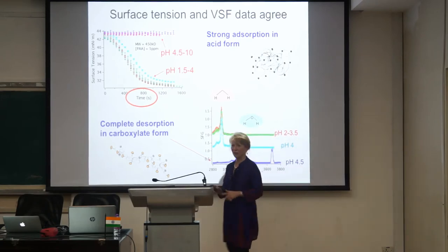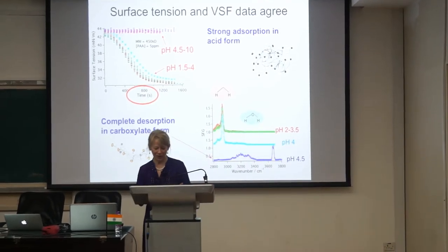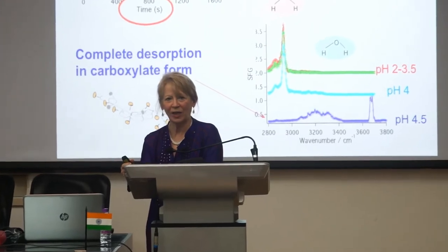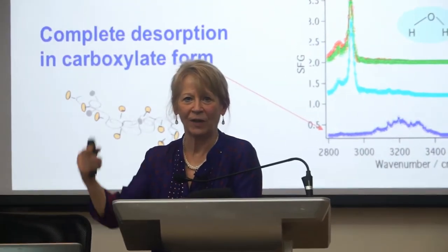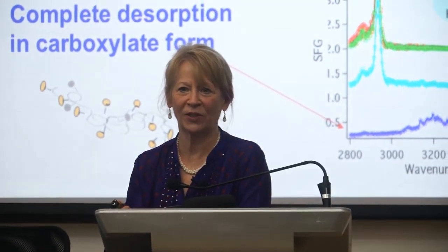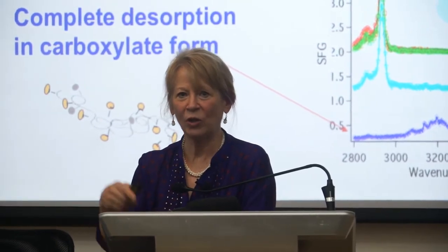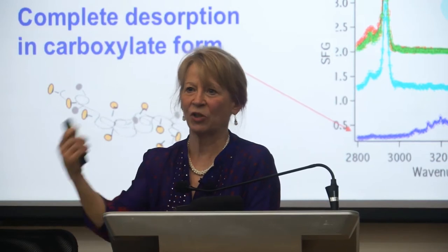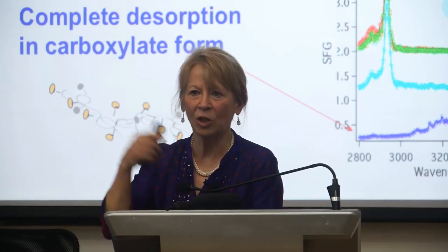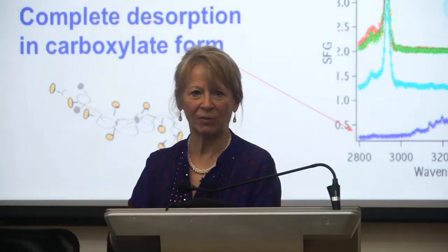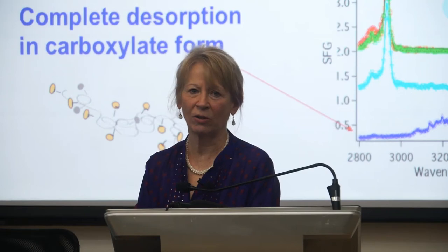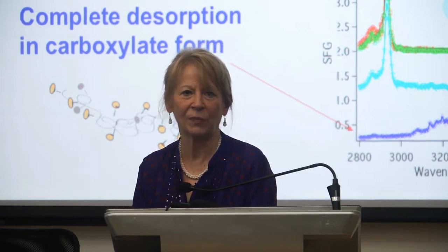So here's the deal. Normally when you think you're going to measure something, you're going to get a signal every time something goes there. Normally you think as more and more stuff goes down that your signal gets stronger. So if I'm measuring how much stuff is there and my stuff is related to my signal, the more polymer goes down there, the stronger and stronger signal I would get. And the surface tension measurement told us that over an hour, more and more of that polymer was going down. But the surface tension isn't sensitive to orientation, it's just how much stuff is there.